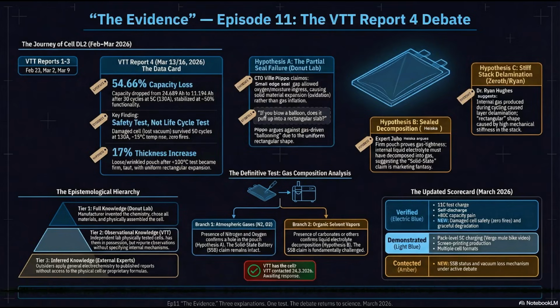So VTT had just finished the 50 brutal cycles at 130 amps. The battery was battered, swollen, and sitting at about 11 amp hours of capacity. Barely hanging on. Then they decided to run one final gentle cycle at a 1C rate, just a slow, steady discharge over an hour. And on that first cycle, the capacity of the battery suddenly jumped by a massive 14%. Wait, it recovered energy that seemed lost? It did. How is that even possible? A dead battery doesn't just spontaneously heal itself.